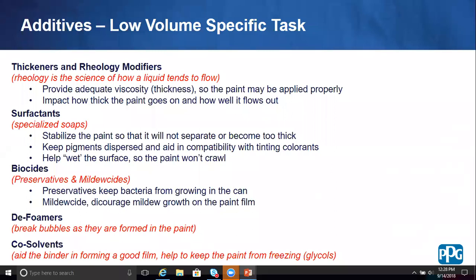Products like Manor Hall or Silk & Touch are made to flow and level very well. So there are rheology modifiers in there that keep them a little bit thinner in the can compared to some other products, but it makes it want to flow and level better. So if you're brushing and rolling, it makes it look like it's sprayed. There's other products like Timeless and Permanizer that have rheology modifiers that keep the paint from sagging, so that if you're spraying the product, you can build it heavy enough to possibly achieve the millage of 2 coats in one, therefore making it a very user-friendly product and it won't sag.